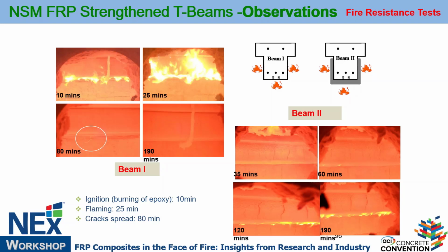If you don't put insulation, in 10 minutes, in spite of having some concrete cover, about 20 millimeter, ignition happens and the epoxy starts to burn. In 25 minutes, it starts to flame. And at 80 minutes, you can see the cracks wide open. But if you put insulation, about 25 millimeters thickness, we used a vermiculite gypsum combination insulation, 35 minutes, no issue here as opposed to 10 minutes, 60 minutes as opposed to 25 minutes. So it lasts longer as well.